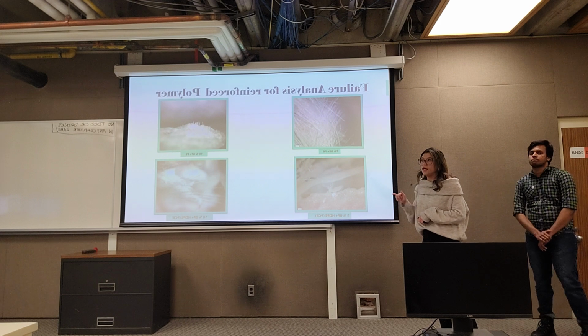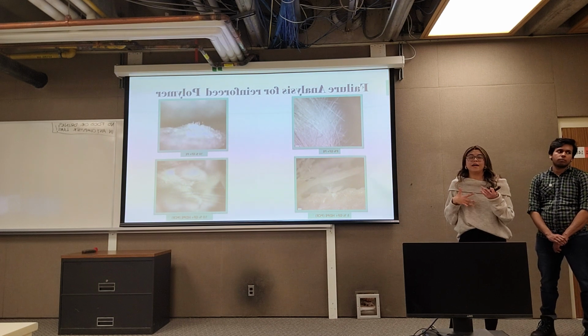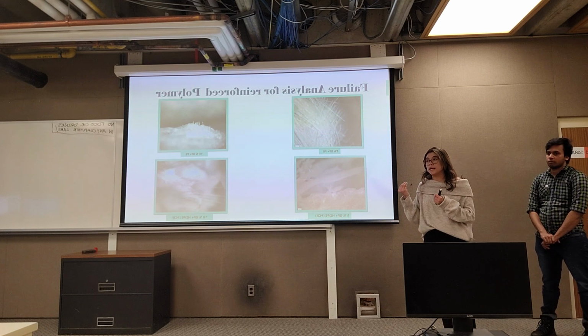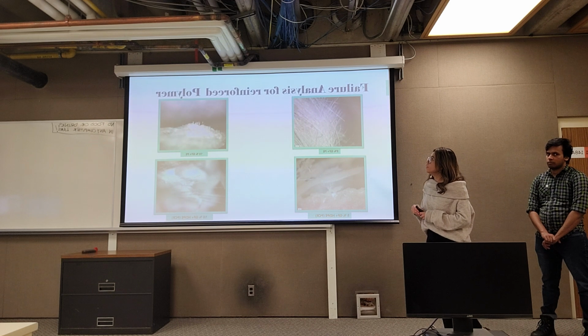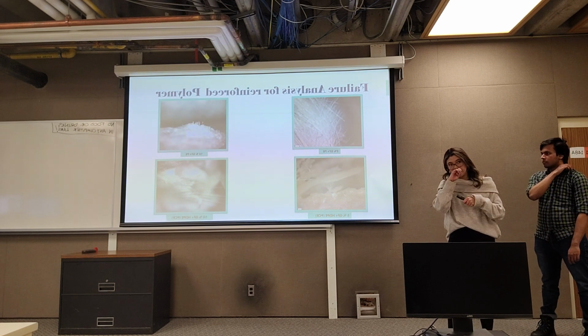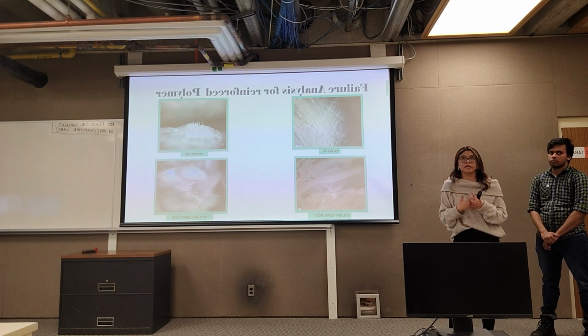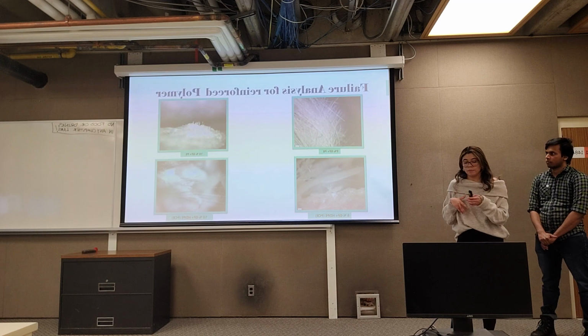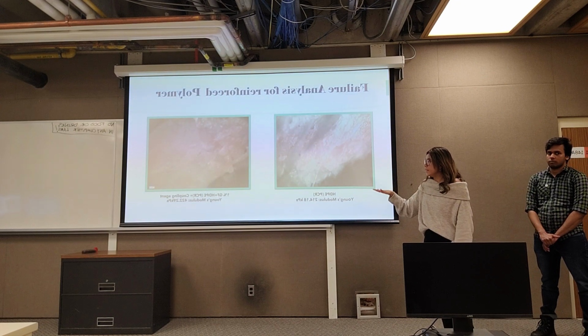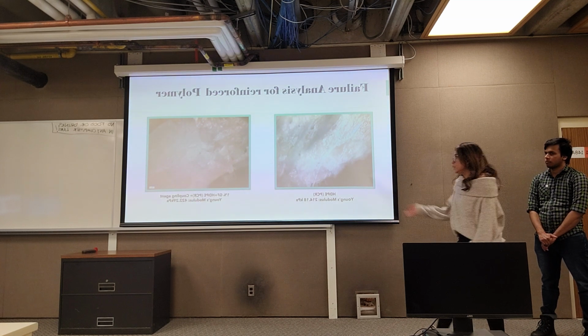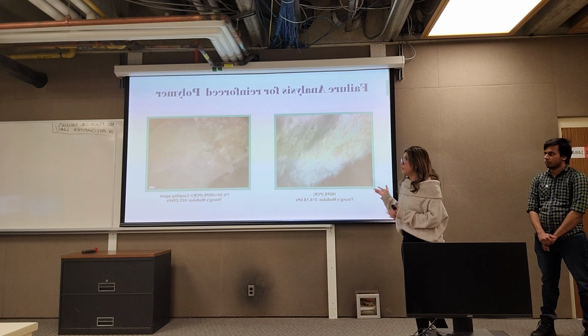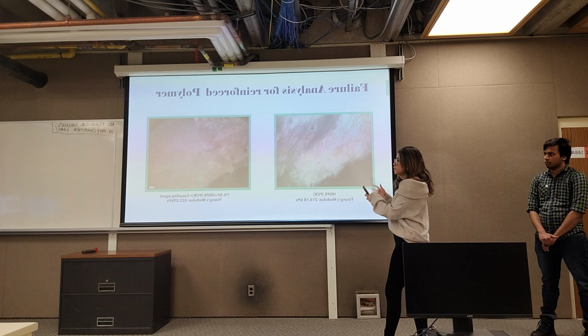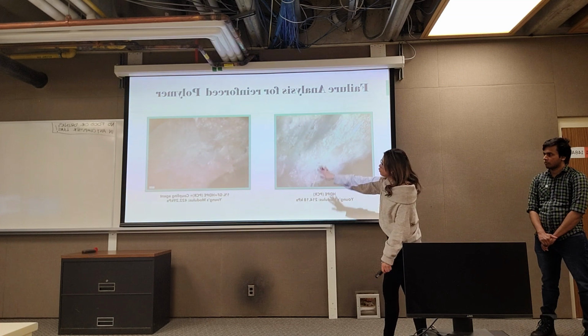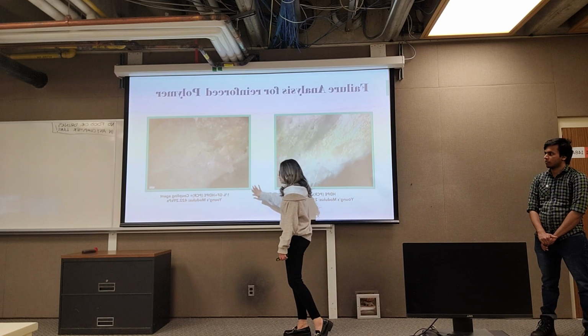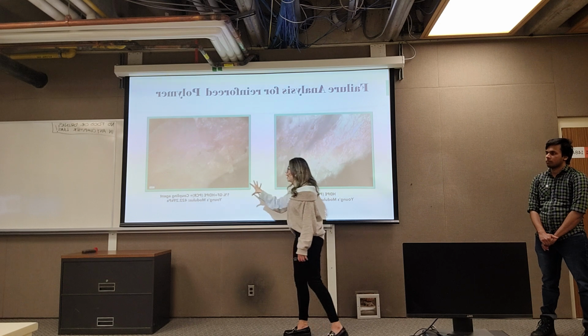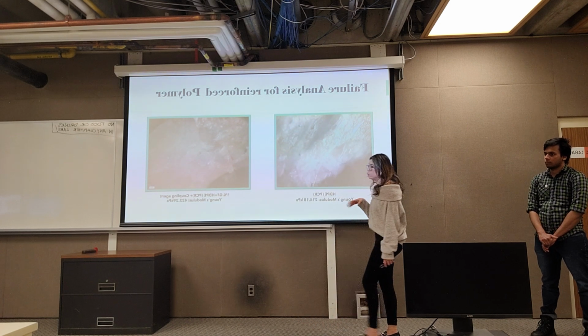This led to an evaluation that we can either include a coupling agent, because there is no good binding between the fiber and the matrix, or that the technique of doing the glass and then feeding it on injection was not giving us a good mixing of the matrix and the glass fiber. So we made another test, adding a coupling agent for 1% glass fiber, and we observed that the failure was not because of fiber pull-out, and instead we observed some jagged edges in the surface. This is also aligned with our results of tensile testing because the Young modulus was higher than the sample without reinforcement.